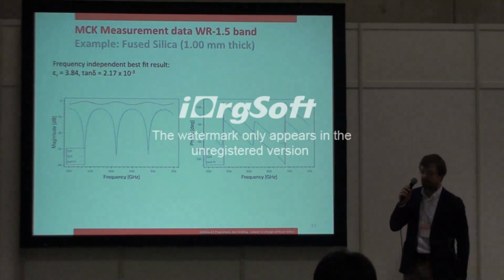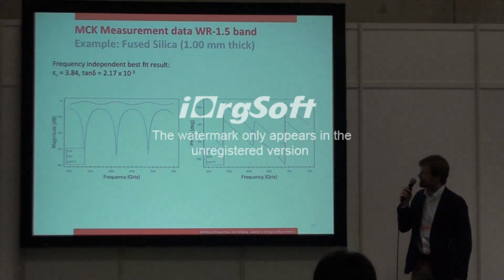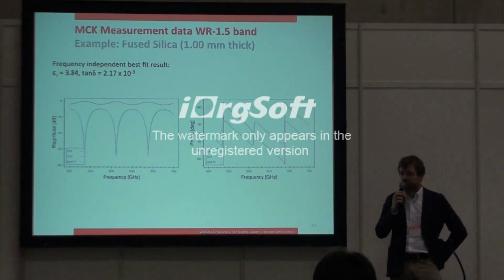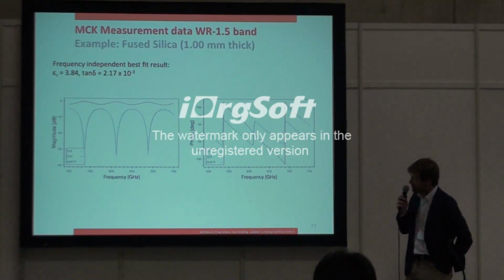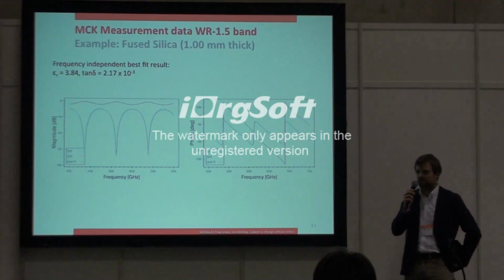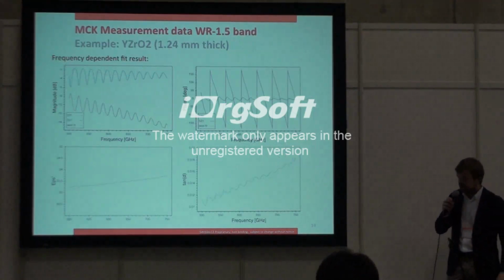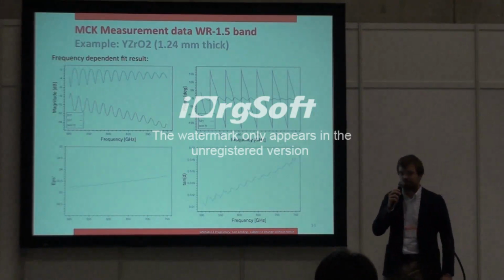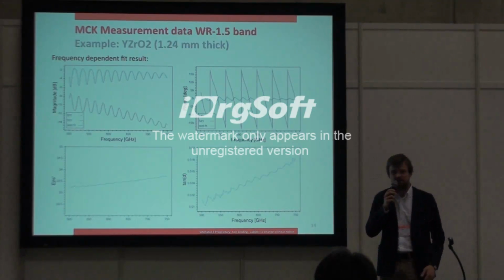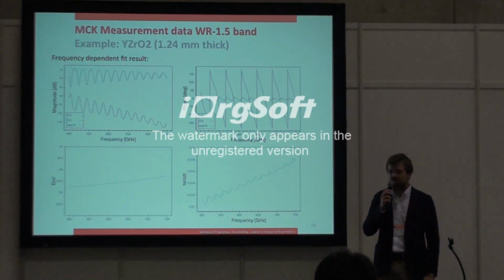A second example of this approach with some fused silica sample, again a millimeter thick. We see magnitude and phase measurements of reflection and transmission, along with the simple constant epsilon and constant tan delta permittivity model. For some samples, this simple model no longer works because, interestingly, these samples have frequency dependence of their permittivity, so non-constant epsilon and non-constant tan delta.